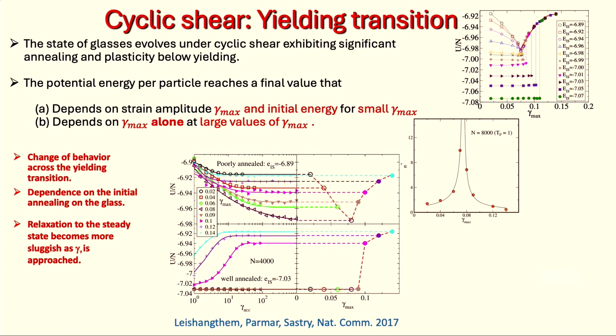And as I already mentioned, the number of cycles that I need in order to reach the final state has non-monotonic behavior and an apparent divergence at the yielding transition. And this divergence of timescales when I'm coming from above is associated with the phenomenon of reaching the fatigue limit upon reducing the load, okay? So the yielding transition as I'm describing it now would correspond to what we might call the fatigue limit, okay?